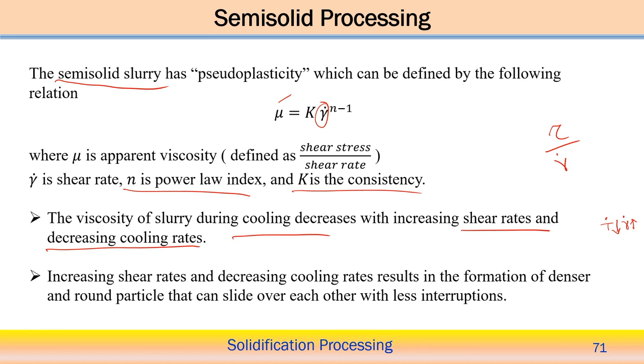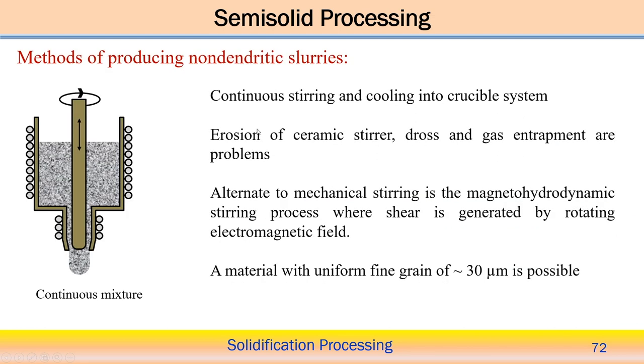Now, increasing the shear rate and decreasing the cooling rate actually results in the formation of dense and round particles, and they can slide with respect to each other with less interruption, because it is easy for round particles in this stack to move and slide with respect to each other. So, we have mentioned here slide over each other without much interruption. This is the typical characteristic we observe during the semi-solid processing of a particular material.